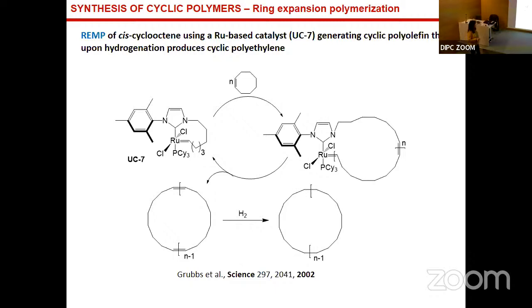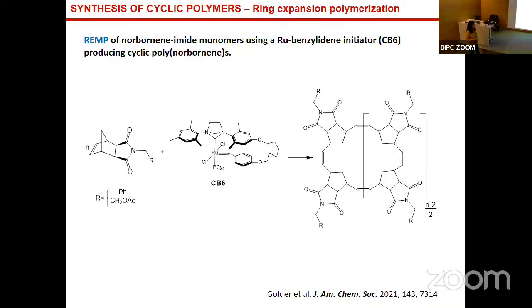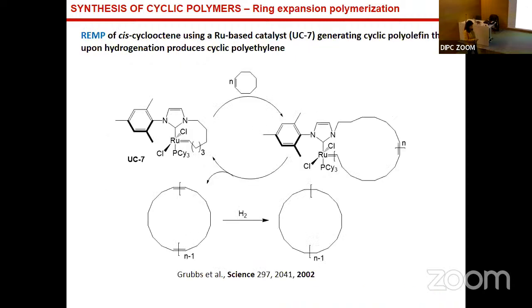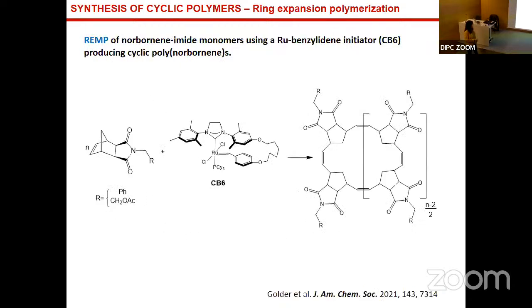This is related to the incorporation of this monomer into the cyclic catalyst of ruthenium. Then this is the polyolefin that's obtained, and by hydrogenation, cyclic polyethylene can be obtained. So there are some modifications of this ruthenium catalyst, for example, by modifying this linker here, and other monomers were also able to be polymerized to obtain cyclic structures, like for example this cyclic polynorbornene. This is a very recent work.